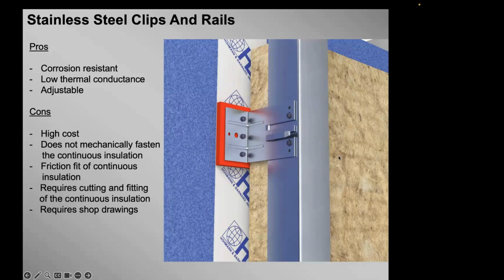Doesn't mechanically fasten the insulation, so you're gonna have to add the insulation retainers. Requires cutting and fitting of the insulation. They show it here, but here they just lay it on top of this red piece. Their thermal isolator, as they call it, but that's going to leave a quarter-inch gap behind your insulation, which you don't want, and it does require shop drawings.